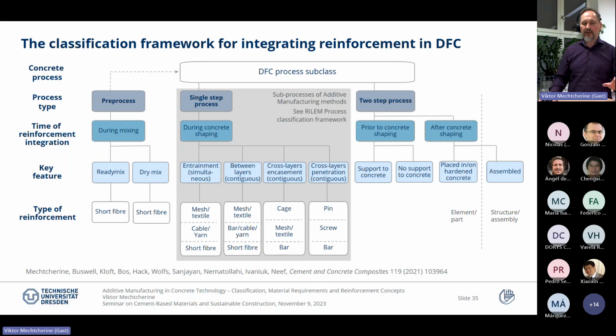It's entrainment, deposition between layers, cross-layer encasement, and cross-layer penetration. And then we have a two-step process. These four were a one-step process where the concrete is still in a fresh state, and we process the reinforcement in parallel or simultaneously. If we separate production of concrete and reinforcement, then we call it a two-step process. And then we have two options: we put reinforcement prior to concrete shaping or after concrete shaping. And I will show you an example for all these approaches.